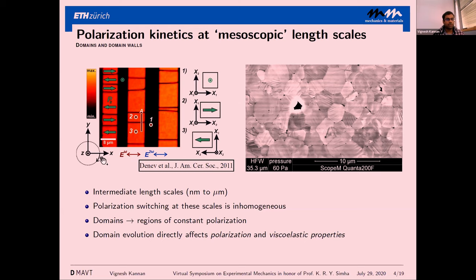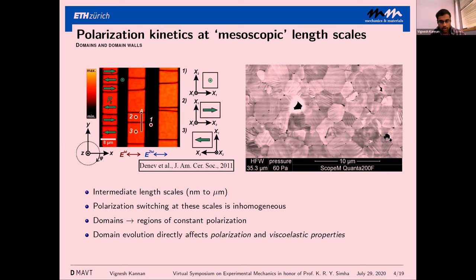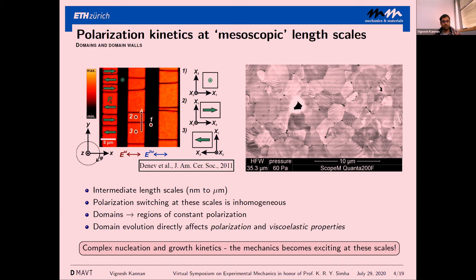The image on the left is from a single crystal of barium titanate using second harmonic generation microscopy. You can see different natures of domain walls. Where my cursor is right now, this would be a 90-degree domain wall, where the polarization reorients by 90 degrees across the wall. Similarly, this would be a 180-degree domain wall. The image on the right is from our barium titanate ceramic samples, which are polycrystalline. You can see intricate domain patterns inside the grains. Studying the evolution of these complex laminate patterns has important applications in designing materials at the technological length scale.